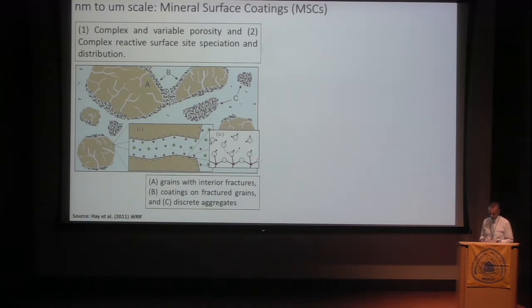and organic matter. And the structure and composition are dependent upon the underlying composition of the grains on which they sit, and then the hydrogeochemistry, the hydrobiogeochemistry happening around it, all of which can result in physically and chemically complex systems. And some key features of them are the formation of intergrain fractures where there could be internal surface area, secondary coatings on top, and then also discrete aggregates.